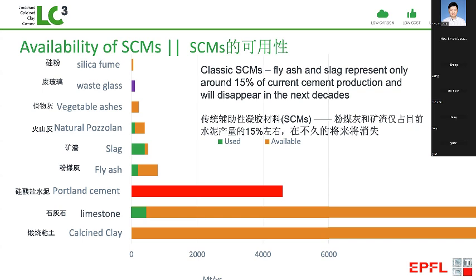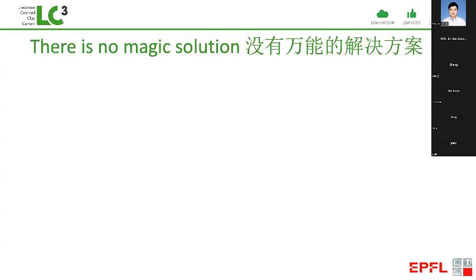What other materials do we have? Well, we have a lot of limestone, which is already used as a substitute material, but we cannot substitute more than about 10% of this without losing the properties. And then when we look at other materials, people have worked on things like waste glass, vegetable ashes, but the amounts of these available are really in very short supply. The only thing we have which is available in the quantities required are clays, which can be calcined, that's to say heated in the range 800 degrees when they become very reactive materials.